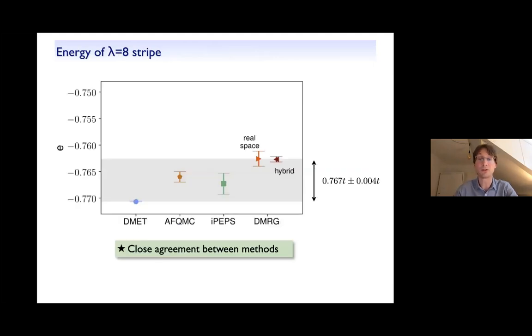Okay, then we can also compare the actual energies of the period 8 stripe, and in the end they all lie pretty close in a narrow energy window here, which is quite remarkable given the fact that all these methods come with their own systematic errors, right? So the error bar here is not a statistical error bar, so we don't expect that results lie within the error bar, because of these remaining systematic errors. But that's really quite a close agreement, also compared to what we had like 5 or 10 years ago when you would compare different approaches.